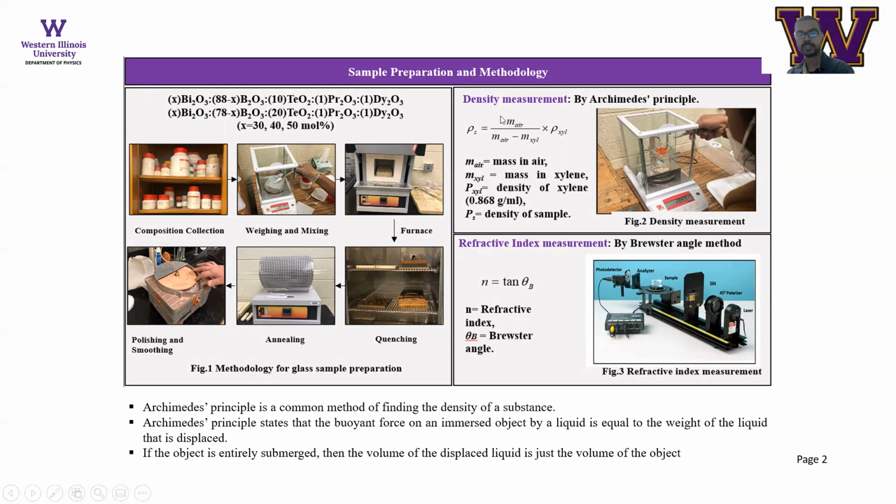So we use these equations for measuring our density. The method is very simple. We took the measurement of our glasses in the air and we took the measurement of our glasses in the liquid, and this time we use xylene as the liquid.